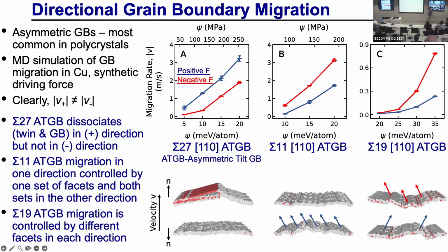In this particular boundary, the sigma 19, well, in the sigma 11, in one case, it's only controlled by one type of facet motion, here by both. In the sigma 19, by the motion of two different facets. Now, why do I show you all that? See, my thought early on was that if I look at the structure, I should be able to see something which is the generic feature of why boundaries are different this way than that way. I always see one kind of difference. The interesting thing is every time I look at a grain boundary, especially more complicated grain boundaries, what you see is that they're different moving this way than that way, but they're different in different ways.